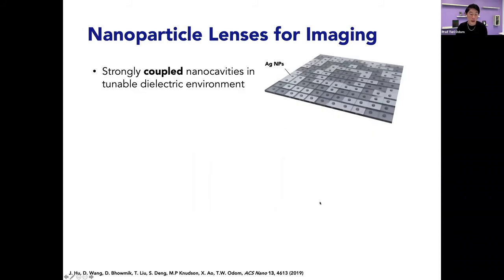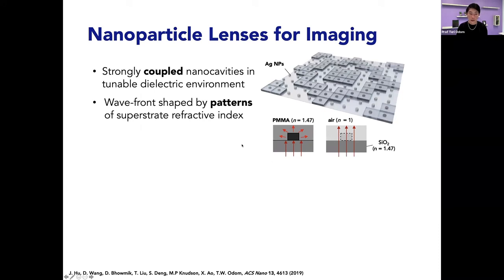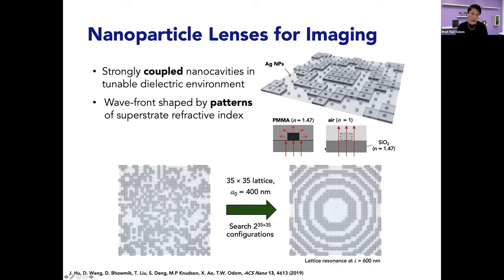Then we wanted to do a little bit better and take advantage of these SLRs that I mentioned earlier, and see if we can locally pattern the dielectric. Because if we do, we're able to control the wavefront just by shaping the dielectric patterns. So for example, if it's surrounded by PMMA, which is index matched to the substrate, you're going to have light that's scattered in plane, and so no light is going to be transmitted. However, if there's just air around the particles, because of this index mismatch, you don't excite the SLR and it just goes straight through.